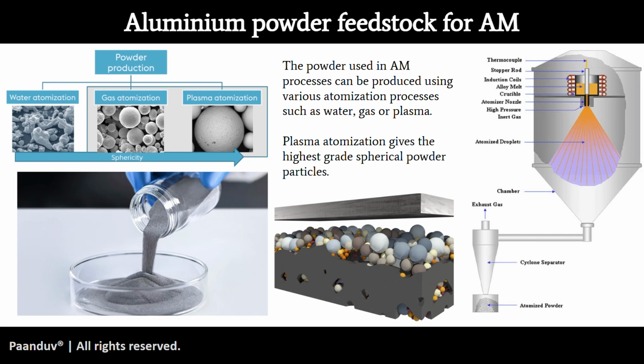If you have a limitation of an atomizer, then such simulation software become even more important, because despite having a poor quality of powder, you still want to have a very good quality of the build. The only option you have is to play around with the process parameters: adjust your laser powers, your inert gas, your chamber conditions, your scanning strategies, your scanning speeds, which is all in your hands. And despite having a poor powder grade, you can still end up having a very good part. For that, you require a good amount of optimization, and AM PravaH can come very handy in such scenarios. Now, that is one way where you can somehow work with poor powders.